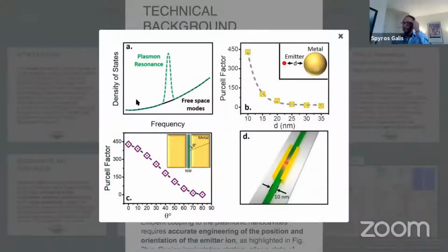So this can be seen in this figure where our numerical calculations, as expected, show that the Purcell factor decreases substantially in figure B here, with increasing distance between the emitter and the metal. And the same applies for the orientation of the emitter in figure C, with respect to the cavity. Here, 0 degrees corresponds to the direction parallel to the axis of the nanowire.